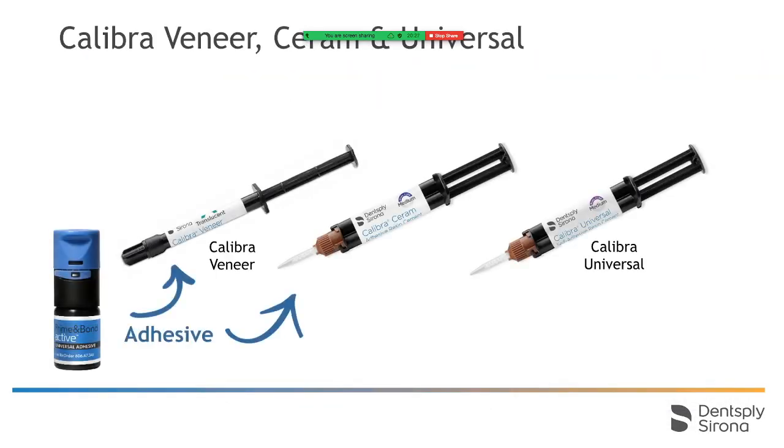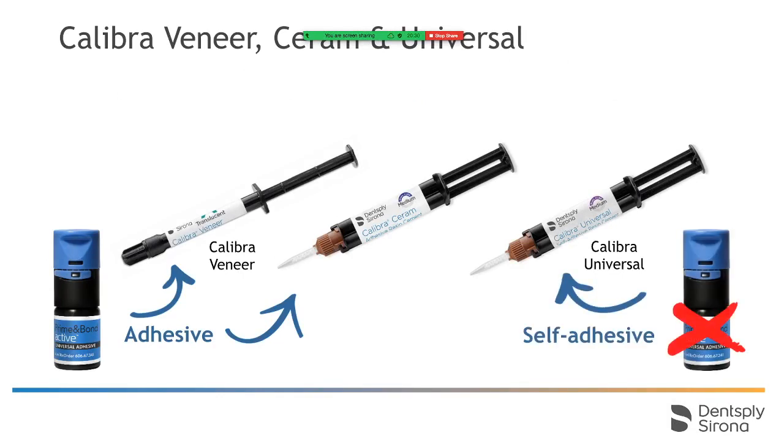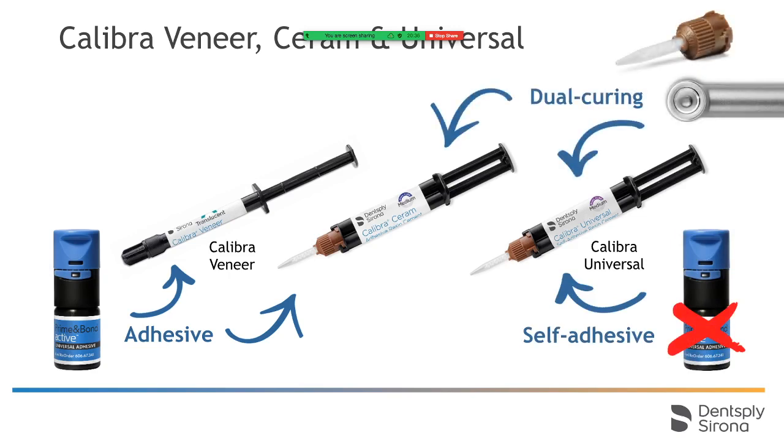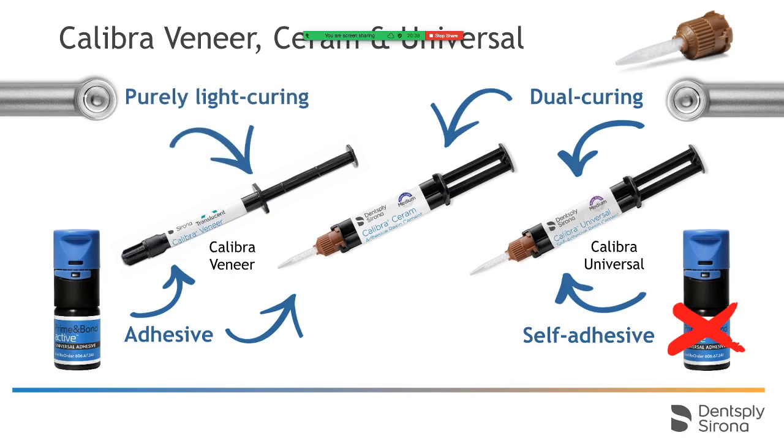We can see the differences between the universal, and Calibra veneers. In summary, the key to successful cementations and preventing post-operative sensitivity with etch and rinse cements: First, don't over-dry the tooth, especially after etching. Limit etching time to 15 seconds only on the dentin. Ensure adequate sealing of the dentinal tubules through proper application of the dental bonding agent. Ensure proper tooth isolation. And when using self or dual-cured resin cements, use a self-cure activator to prevent incompatibilities between the amine initiator and the acidic monomers.